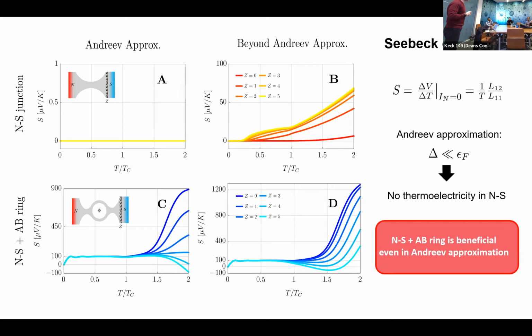So here, TC is the cold bath temperature, right? Not the critical temperature. Actually, this is the linear response regime, so delta T doesn't really play a role. Actually, I plotted as a function of T over Tc. So let's say that up to 1, you are in the superconducting regime because the gap is open. After 1, instead, is the metallic regime. Indeed, if you go to higher temperatures, you approach the metallic behavior of the Seebeck coefficient, which is linear in temperature. So for T over Tc greater than 1, you basically have the normal metal. Indeed, exactly. Perfect.